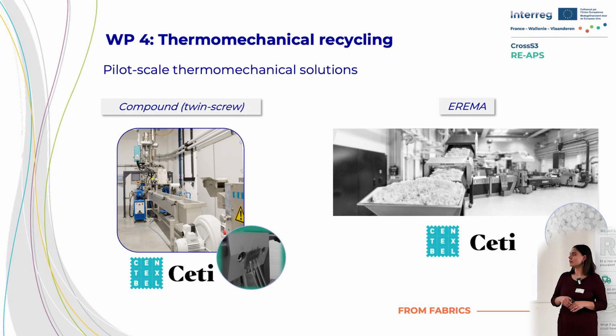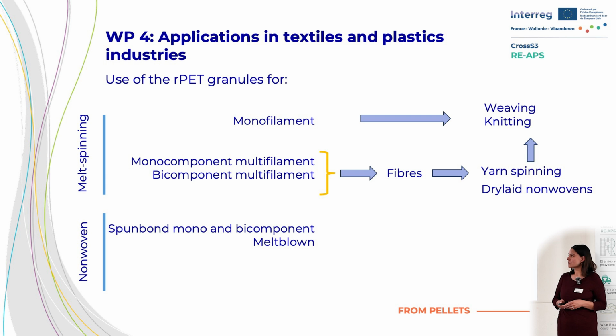Among our platforms, we have a compounder, a twin extruder, which you can see over there on your left. And here is a picture of our EREMA line. This allows us to go from fabrics. Within the applications in textiles, there are 2 main routes. There's either melt spinning or non-woven production. Within the melt spinning, we first take the rPET granules, a monofilament or a multifilament, which can be monocomponent, and then we can go from that onto fibers and be knit or produced via the dry-laid process, or we can go the melt non-woven route, spunbond and processes to go from our pellets into new fabric.